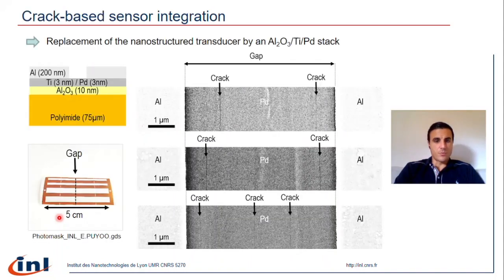At the beginning of the project, our first objective was to replace the nanostructured transducer based on platinum nanoparticles. The precursor that was used to grow this transducer was indeed highly expensive, and it was also not very stable over time. So we have decided to replace this transducer by an alumina titanium palladium stack by combining atomic layer